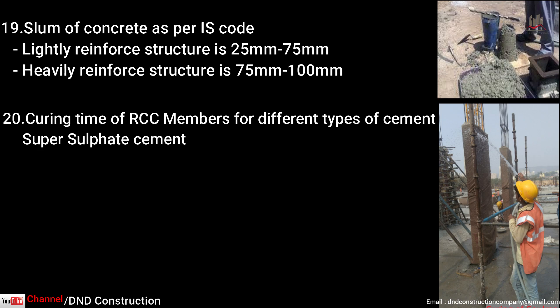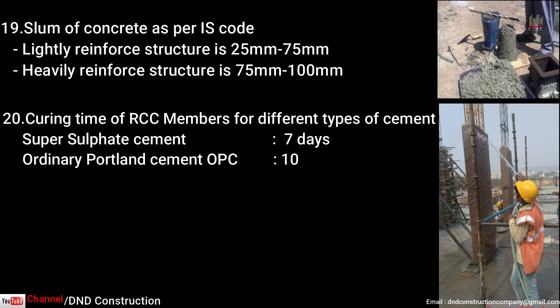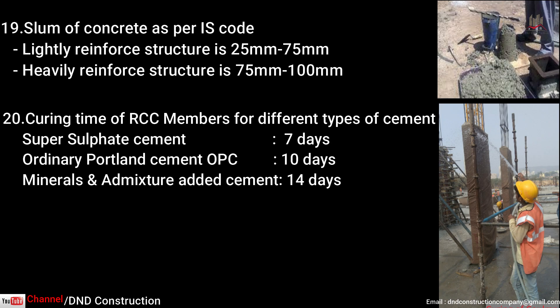Point twenty is curing days required. Curing is necessary to increase the strength of concrete and to decrease permeability of hardened concrete. Curing is done to maintain optimum moisture content. Curing period: for super sulphate cement, 7 days; for Ordinary Portland Cement (OPC), 10 days; and for mineral and admixture-added cement, 14 days.